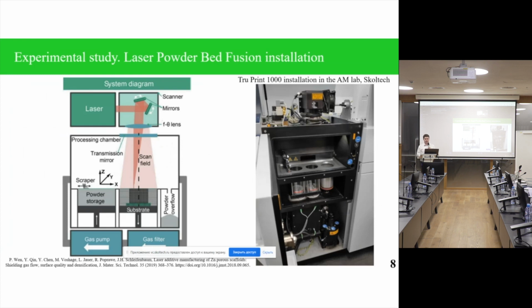So in our laboratory of additive manufacturing at Skoltech, we have a TRUMPF TruPrint 1000 installation that was used in the experimental study. This machine has a nowadays classical system based on 3 cylinders inside. One cylinder is for the powder storage, another one includes the substrate or building plate, and the third one is for the excess of powder. And the final part is received by repeating the same cycle. So we deposit the powder on top of the substrate, then the laser scans this layer and remelts it. Then the substrate goes down, and this process is repeated again and again.